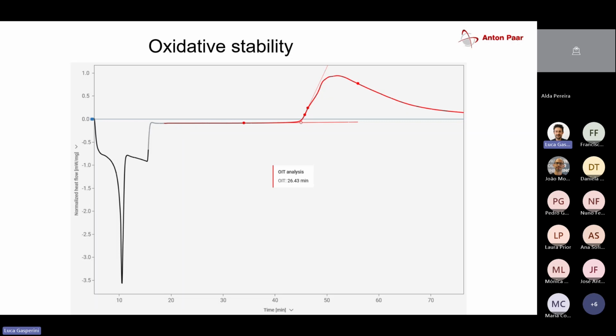Then we switch to an isothermal mode for 5 minutes in order to equilibrate the temperature of the sample. That's the gray part. And once we are receiving a horizontal line in there, once equilibrated, we switch the nitrogen to air or oxygen and keep monitoring the heat flow. After about 26 minutes after we've switched, we see again an exothermic reaction taking place, and that actually denotes the oxidation induction time of this material being 26 minutes.